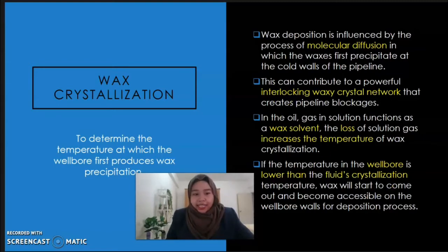So in the oil, gas in solution functions to some degree as a wax solvent. The loss of solution gas increases the temperature of wax crystallization. So if the temperature in the wellbore is lower than the fluid crystallization temperature, wax will start to come out and become accessible on the wellbore for the deposition process.